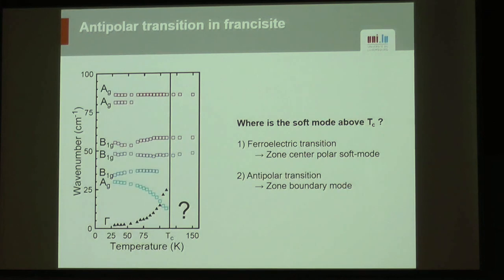Now, classically, if we want to look for this mode in the high symmetry phase, there are essentially two options. Either this transition is ferroelectric, in which case we should be able to see this mode in infrared spectroscopy here, or it's really antipolar, and then this mode is at the zone boundary and can no longer be followed by the classical optical spectroscopy techniques, which is why we went to inelastic X-ray scattering.